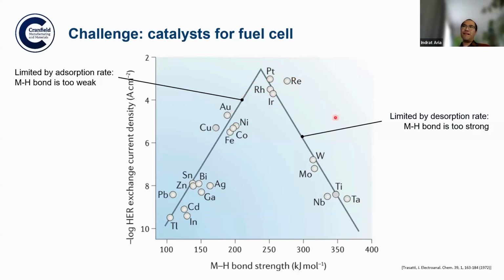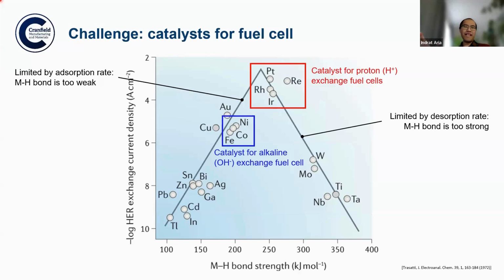If you look at the center there, all of these materials are platinum, rhenium, rhodium, iridium. These are what we call platinum group metals, very rare and very expensive. Unfortunately, those are the catalysts that we use for proton exchange fuel cells or proton exchange electrolyzers. The good thing is that there's an alternative. It's not as good as the platinum group, but nickel, cobalt, and iron are also alternative catalysts. In fact, they have been used for alkaline exchange fuel cells or electrolyzers. They cannot be used in proton exchange because nickel, cobalt, and iron dissolve in low pH, in an acidic environment, so they can be used in an alkaline environment. However, the catalysts are not as efficient or effective as those of platinum group metals.